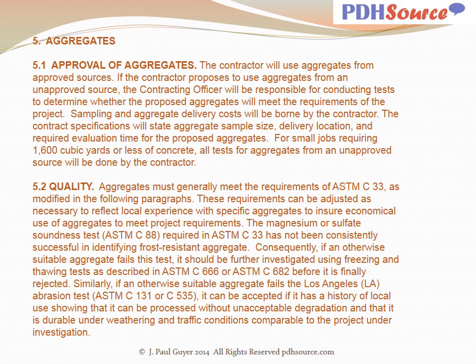Similarly, if an otherwise suitable aggregate fails the Los Angeles abrasion test, ASTM C131 or C535, it can be accepted if it has a history of local use showing that it can be processed without unacceptable degradation and that it is durable under weathering and traffic conditions comparable to the project involved.